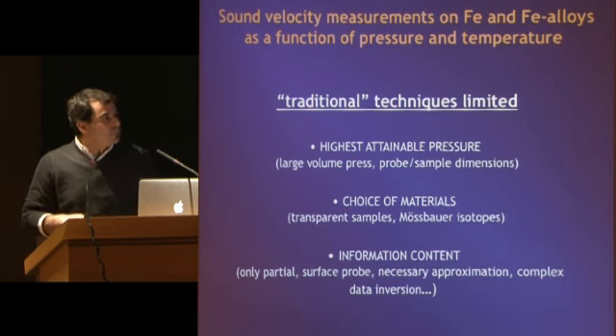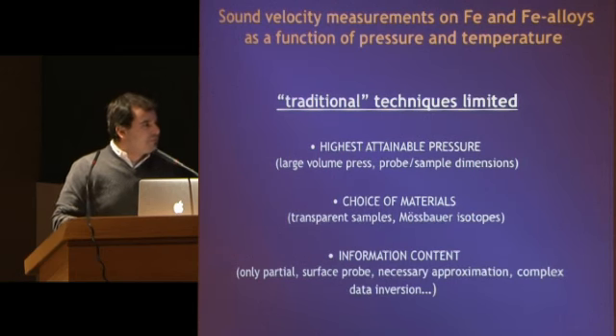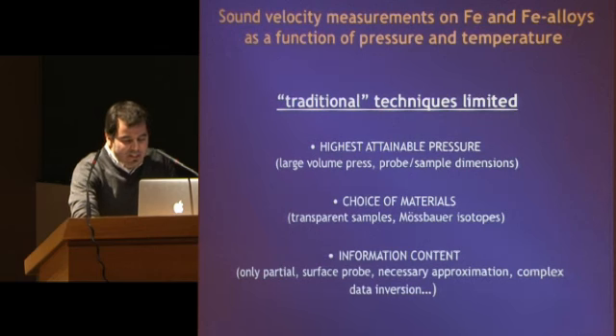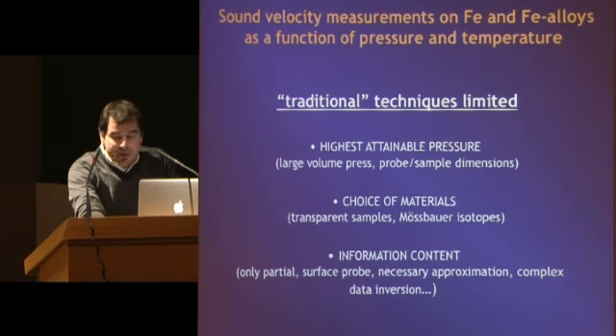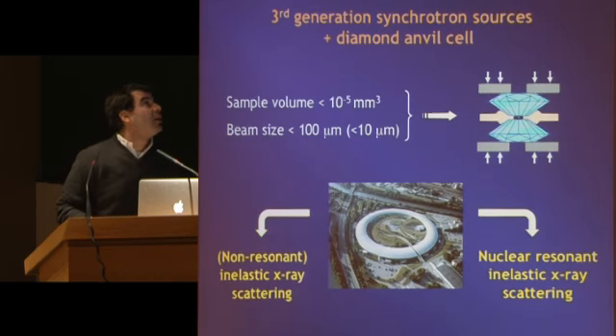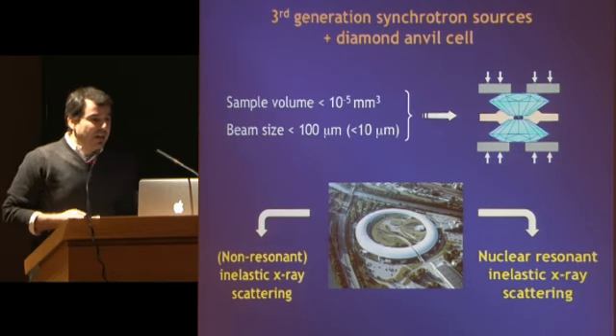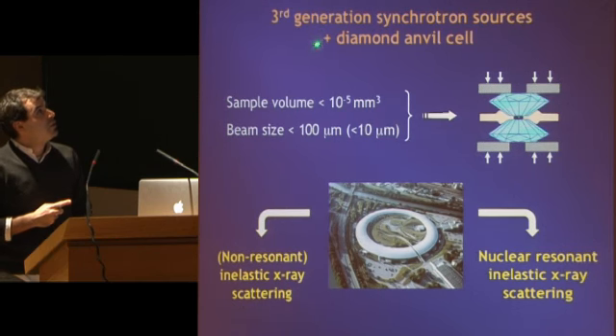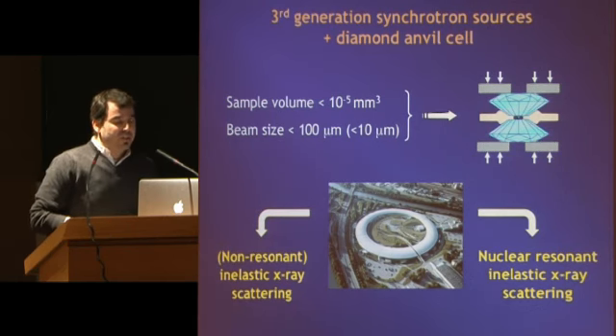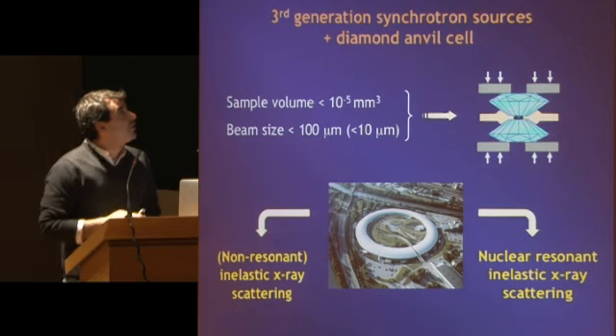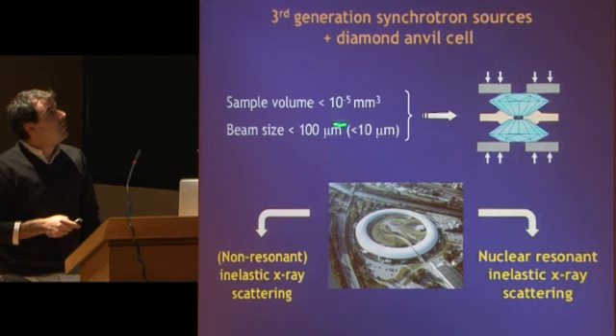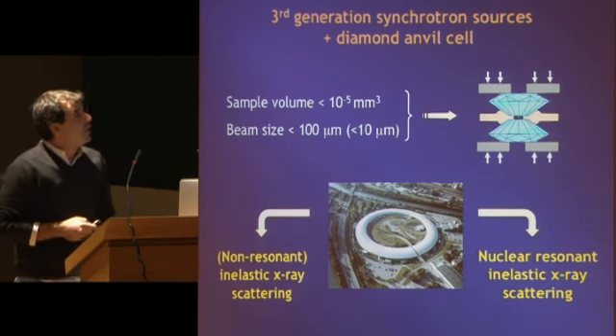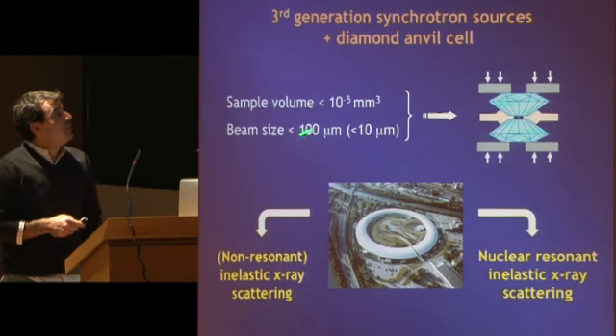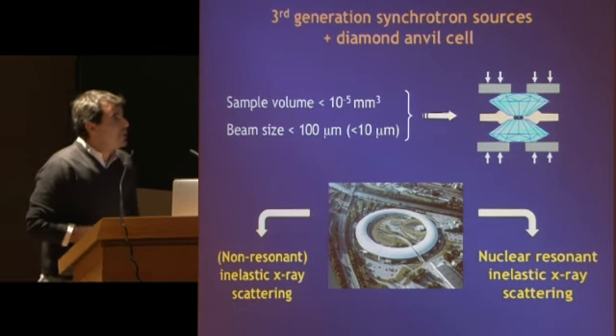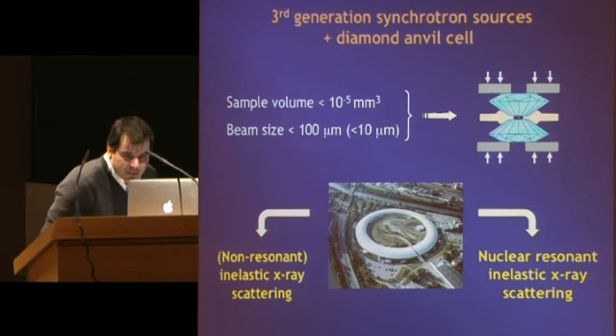Other techniques like radial diffraction involve quite complex approximations, so that basically all these technical difficulties prevented measurement of sound velocity on iron and alloys at megabar condition up to the beginning of 2000, when two major technological advances allowed this measurement. The first is the third generation synchrotron source, and the second is the diamond anvil cell technology. So thanks to the brilliance of third generation synchrotron sources, samples with volume smaller than 10 to the minus 5 cubic millimeter can be probed. And basically, irrespective of the technique, the X-ray beam can be focused down to 100 micron, and for many techniques even below 10 micron, thus allowing the use of a diamond anvil cell.